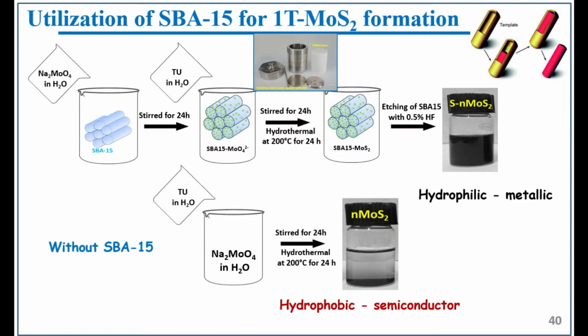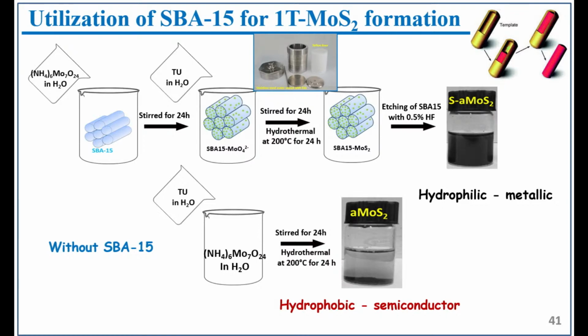But if you are not employing SBA-15, you are producing a hydrophobic part. So that means it's a completely 2H part. Similarly, we use ammonium molybdate as a precursor and thiourea. In this case also, we are getting the hydrophilic metallic phase inside the SBA-15, and then without any SBA-15 you are producing a semiconductor material, the MoS2.